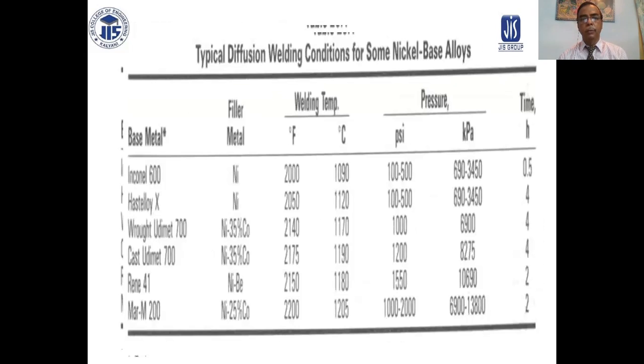Typical diffusion welding conditions for some nickel-based alloys. This is Inconel 600. The filler material is nickel. This is 1090 degrees centigrade, 100 to 500 psi, and 0.5 hours. Next alloy, this is a nickel alloy, 1120, 100 to 500 psi. This is 4 hours required. Pressure.